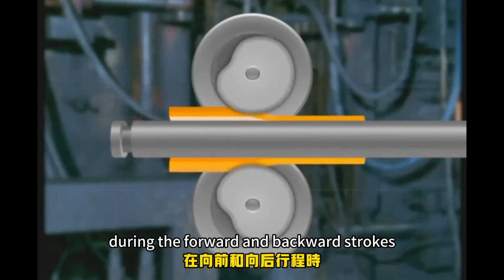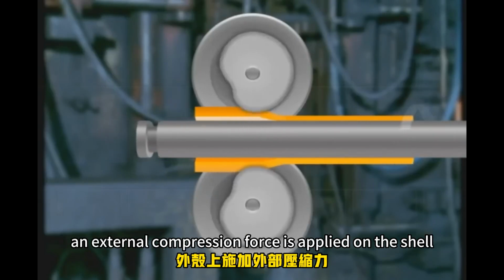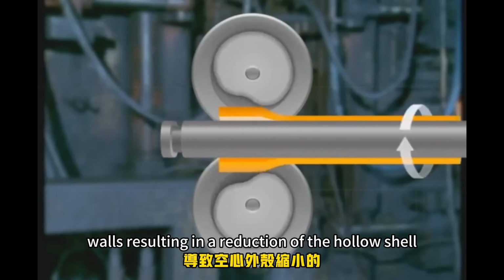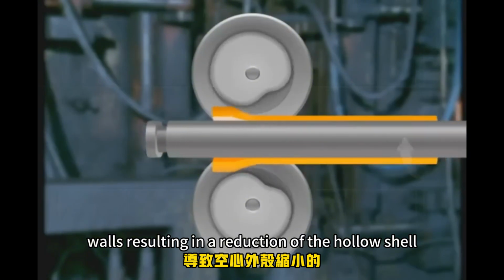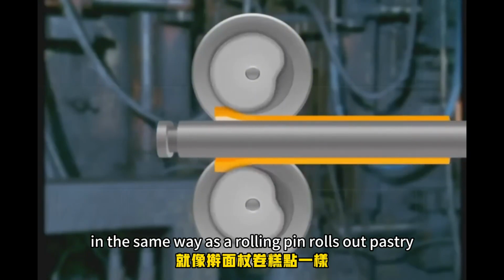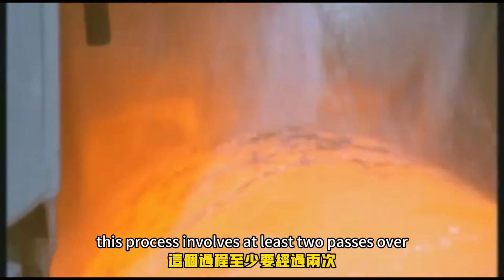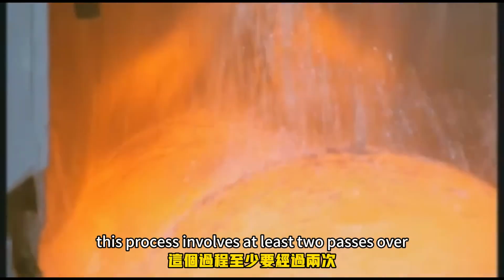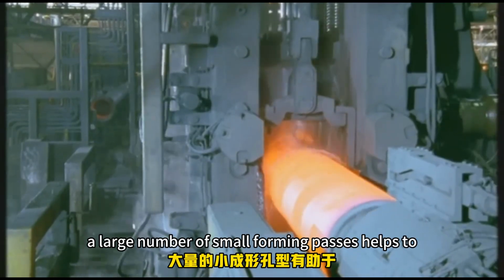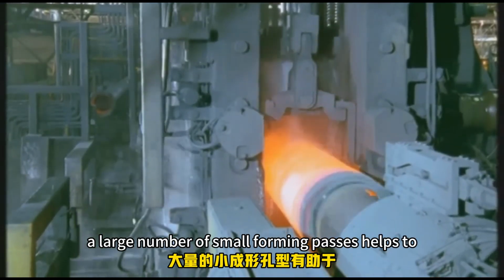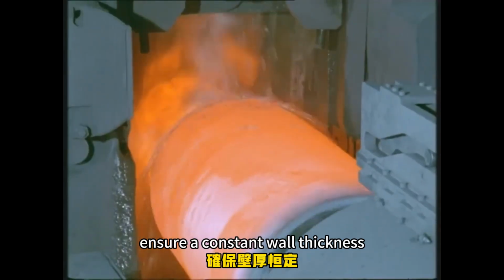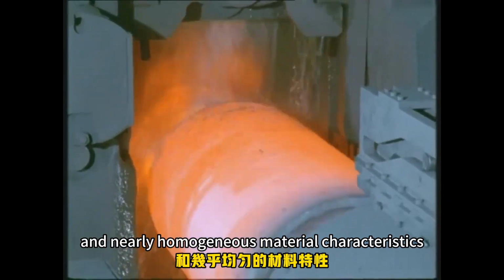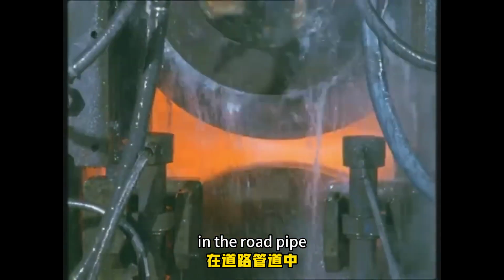During the forward and backward strokes, an external compression force is applied on the shell walls, resulting in a reduction of the hollow shell wall thickness in the same way as a rolling pin rolls out pastry. This process involves at least 2 passes over each material particle. A large number of small forming passes helps to ensure a constant wall thickness and nearly homogeneous material characteristics in the rolled pipe.